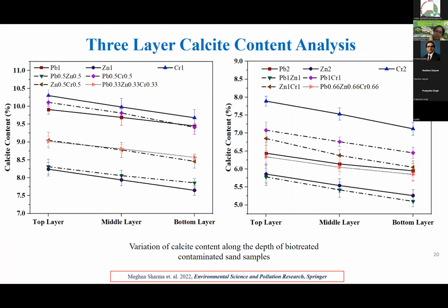Okay, the same thing happened as in the other strength results also, like the 3-layer calcite precipitation, where uniformity is still a matter. In all the combinations, uniformity in calcite precipitation was achieved, but in zinc contaminated soil samples, the amount of calcite precipitation was a bit lesser, or in multiple combinations where zinc was present, the amount of calcite precipitation was lesser. So zinc was found highly toxic to the bacteria.